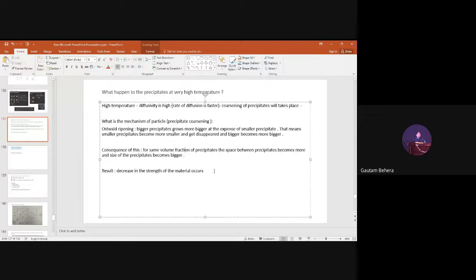So you understand, the gap between the particles will increase because the volume fraction is fixed. If a smaller number of particles is there, we are left with bigger particles, and the space between the particles increases. So dislocations will find an easy way to cross the particles. The strength will decrease like this. Already written over here: consequence of this, for the same volume fraction of precipitate, the space between the precipitates becomes more, and the size of the precipitate becomes bigger. So here the strength of the material decreases, right?